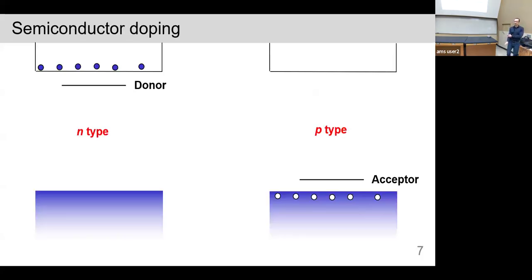So really, to make semiconductors useful, you need to dope them. And so we have 2 types, N-type and P-type. So if you put in a deliberate contaminant or a dopant, which is a donor impurity, it has 1 extra electron. For example, phosphorus in silicon. So phosphorus has 5 valence electrons. It replaces a silicon that has 4. So that extra electron is available to go into the conduction band. So a little bit of thermal energy is enough to put the electron into the conduction band. So you put lots of donor impurities in your material.